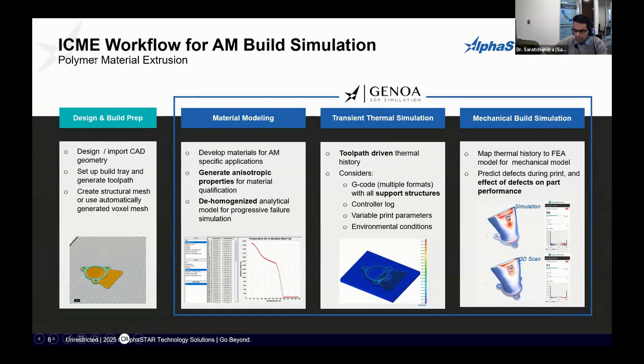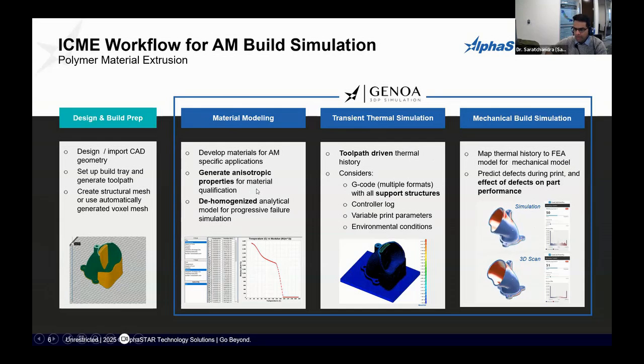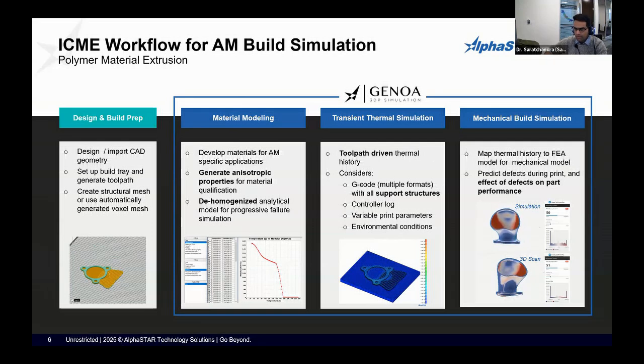This slide talks about the workflow that we use in order to achieve this. So on the left, we see our design and build prep. So this would be your typical design your geometry in CAD, set up your build tray, slice it, and then normally at this point you would send it to the printer. But instead, on the right is our GENOA 3DP ICME workflow, where we start all the way from material modeling, and we generate anisotropic properties for material qualification. So if you have a fiber filled system, for example, you can utilize our material modeling toolset to generate all the required anisotropic properties, and also generate temperature dependent properties, and then feed that into the rest of the simulation.